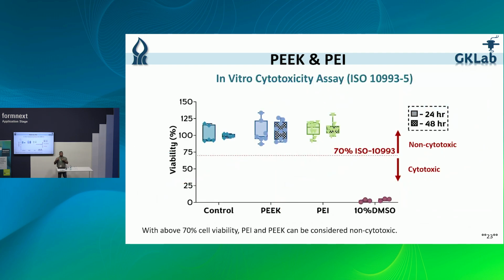And as I mentioned earlier, these materials are designated to be used for implants, and this is an example from one of the biocompatibility tests we are performing. This is an in vitro indirect cytotoxicity assessment, and as you can see, the cell viability for both materials is well above 70%, and this, in fact, according to this standard, shows us that these materials are non-toxic, and it shows us promising results that these materials can be used for future implants.